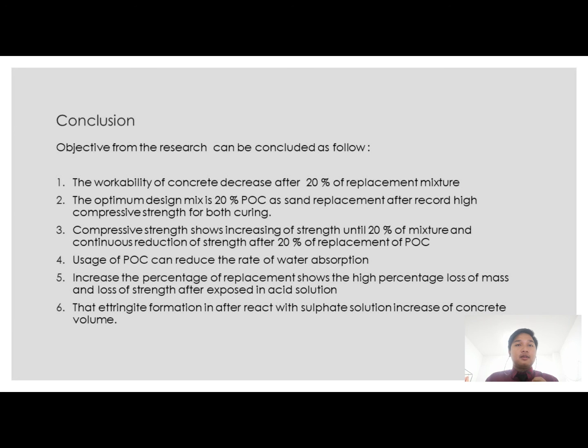Third, compressive strength shows increasing strength until 20% of the mixture, and continuous reduction of strength after 20% replacement of POC. Usage of POC can reduce the rate of water absorption. Increasing the percentage of replacement shows a higher percentage loss of mass and loss of strength after exposure to acid solution. The last one is that ettringite formation after reacting with sulfate solution increases the concrete volume.